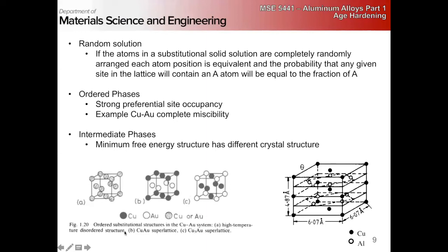Then we also have potentially intermediate phases where the minimum free energy structure is a different crystal structure, and it's typically in between the matrix and something else. And we'll talk about this with aluminum when we have intermediate phases of theta double prime and theta prime, which are in between the FCC aluminum matrix and the thermodynamic equilibrium theta phase, right?